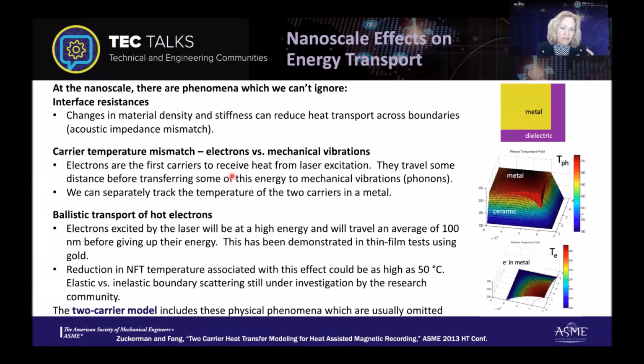And then while these electrons have a different temperature than the lattice, they're called hot electrons, and they can actually travel about 100 nanometers before they end up interacting with either another electron or the lattice. And so this is actually fairly efficient transport across that length. This is actually a positive effect because those hot electrons can transfer some of that energy away from the PEG. And this actually has the effect of cooling the device, or at least the PEG. It gets some of the energy out into the disk instead of all staying in that localized PEG area. And so all of these, we'll see how much of an effect they have in the next slide, but these are effects that happen only because we're at these very short time and length scales, but they have a material impact on the temperature of the device.